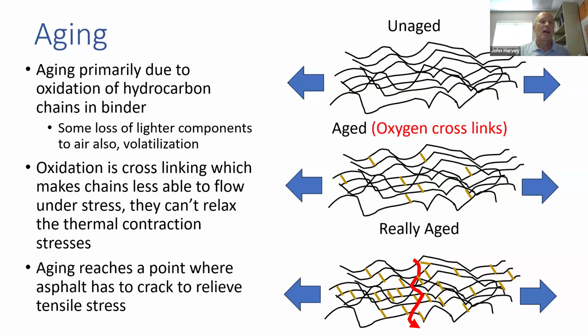Asphalt pavement is particularly weak in tension. So when the asphalt is contracting because it's getting cold and that contraction is restrained, then that puts that asphalt material in tension. If the asphalt is really stiff, the stress from that contraction is going to be higher. And if that stress is higher than the strength, then you get a crack, an age-related crack. So what has aging got to do with it?